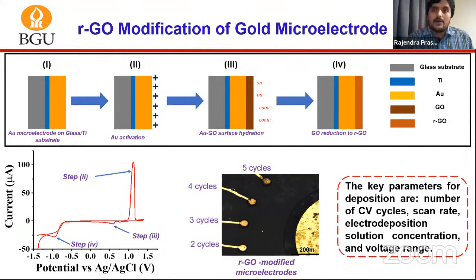Another modification is modifying the microelectrodes with reduced graphene oxide, and here I used the cyclic voltammetry technique, and the solution was graphene oxide and NaCl. NaCl was used as an electrolyte. So what happens basically in the first half of the cycle, the gold surface is activated by the chloride ions. And in the other half of the cycle, the graphene oxide has negative functional groups present, and they are attracted to the activated gold surface. And when we have the negative scan, these negative functional groups are repelled away from the surface, leaving behind the carbon layer on it.